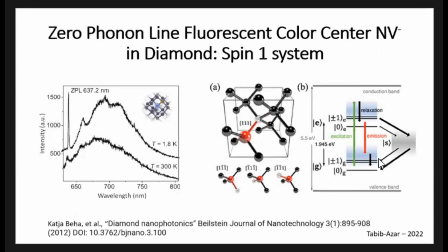If you apply the 2.87 gigahertz pulse, you suppress this luminescence. This is the basis of optical detection of magnetic resonance. If you apply 2.87 gigahertz, you take the electrons, unpair them, and put them in plus or minus spin states, and the luminescence goes down. So that's one key thing: it is the basis of optical detection of magnetic resonance, or electron resonance in this case.